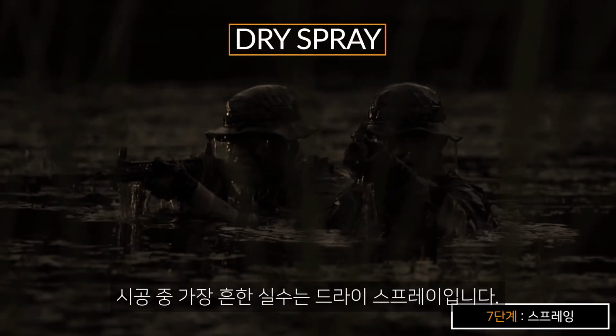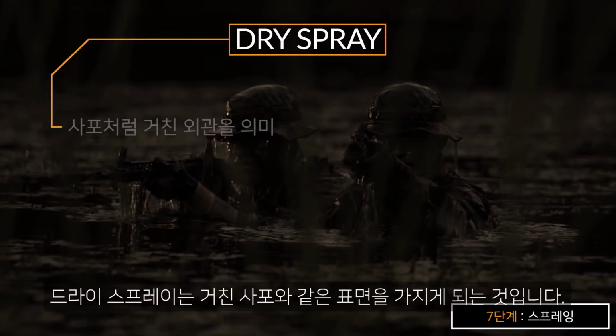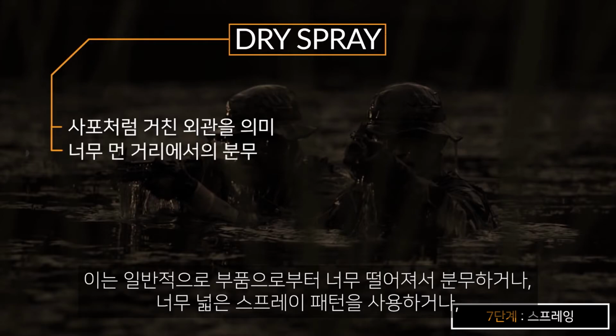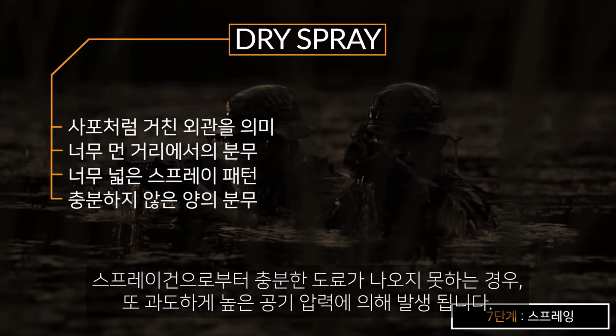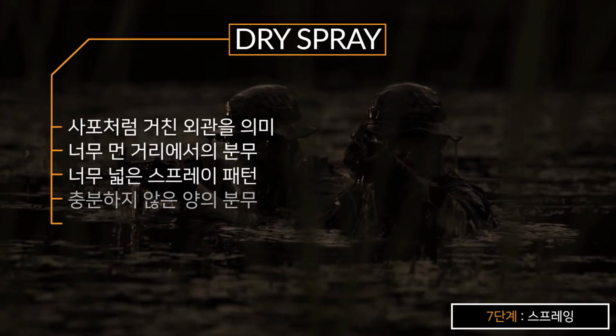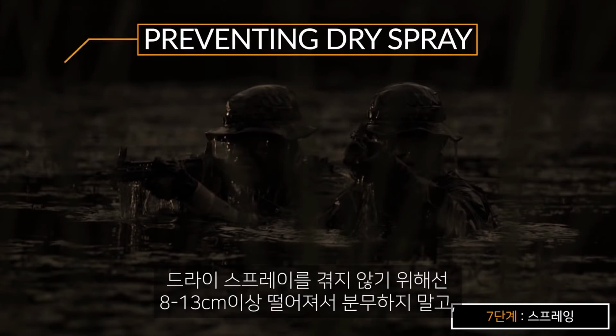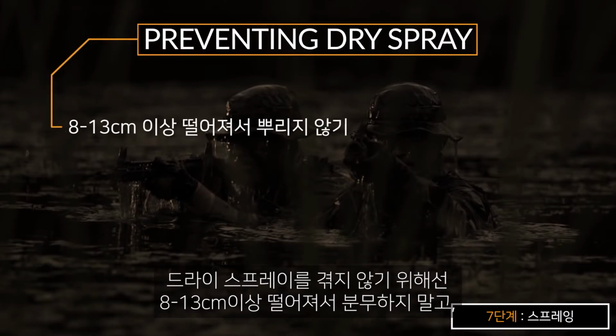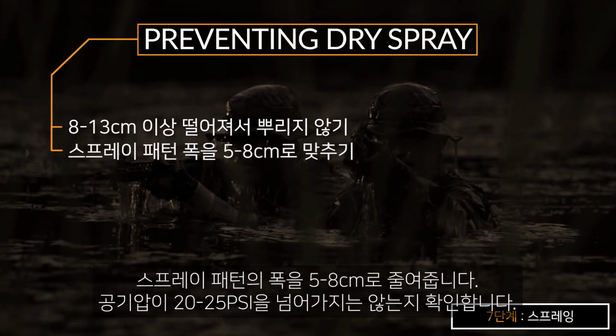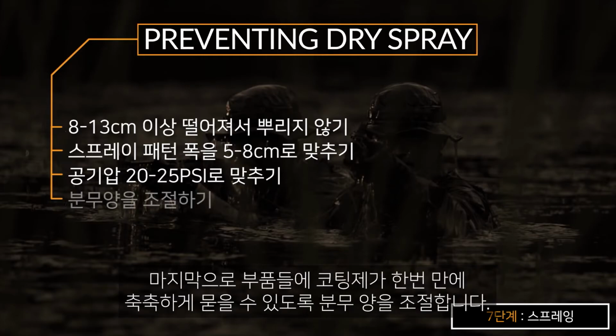The most common application mistake is dry spray. Dry spray has a rough sandpaper-like appearance and is typically caused by spraying too far away from the part, too wide of a spray pattern, not enough material coming out of the gun, or too much air pressure. If you experience dry spray, ensure you are no further than 3 to 5 inches away from the part. Reduce your spray pattern to between 2 and 3 inches wide. Check that your air pressure is no higher than 20 to 25 psi. And finally, adjust your fluid control to ensure you have adequate coating material being applied to wet out the part in one pass.